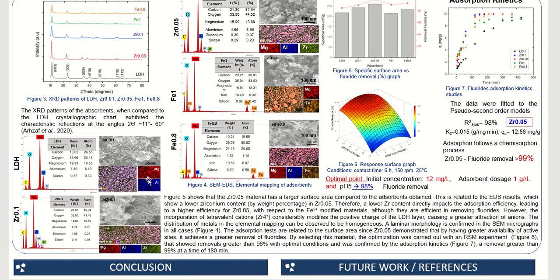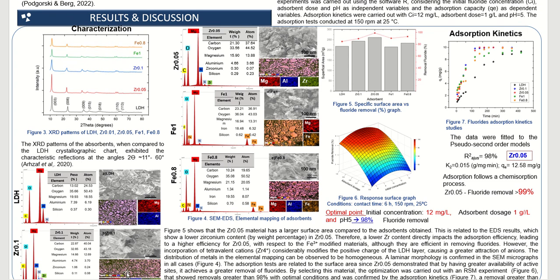Figure 4, where a greater dispersion of zirconium is shown in zirconium 0.1 than in zirconium 0.05. The same tendency is observed with the results of the specific surface area, since zirconium 0.05 has a greater area with respect to the other materials. This is reflected in the removal of fluoride, which was higher with the zirconium 0.05 material, as observed in graph 5.